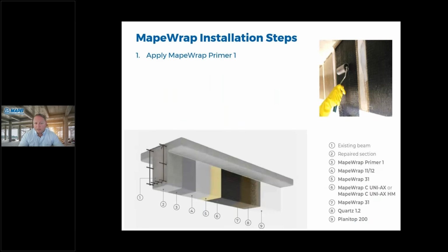So some installation steps for the MapeWrap fabrics. You're going to apply a primer. You're going to use this epoxy adhesive. This is a thicker epoxy. We have MapeWrap 11 or MapeWrap 12, and these are formulated for different temperature zones. So depending on the temperature of your project site, you're going to want to select the correct one to make sure that you have the ideal working time for those that are going to be installing the system.